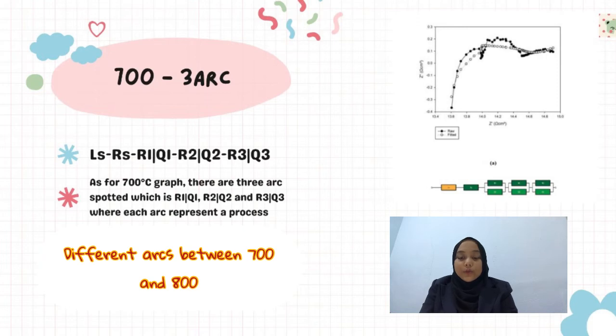In R1, Q1, it represents an electronic charge transfer at the cathode surface, while in the R2, Q2, represent the ionic charge transfer at the cathode, and at the last arc, which is the R3, Q3, it represents the charge transfer operation such as oxygen ion diffusion in the cathode bulk and oxygen ion incorporation from the three phase boundaries.